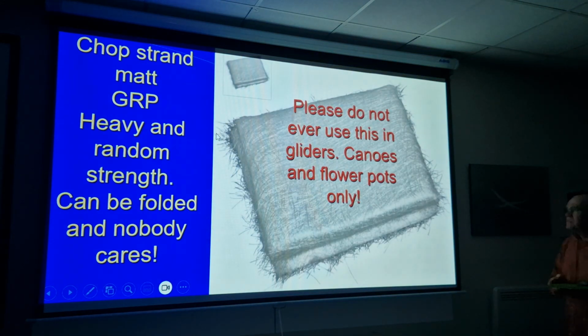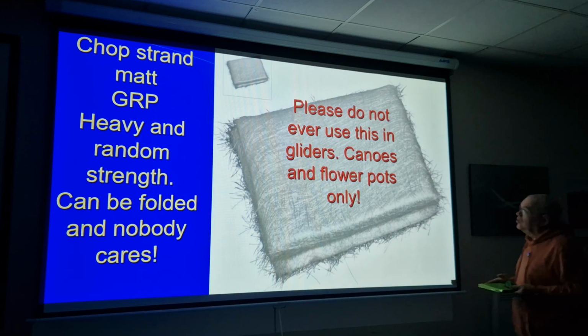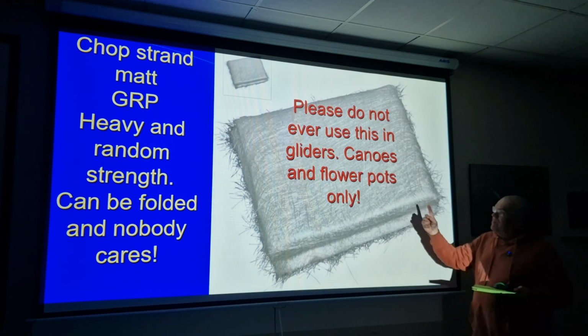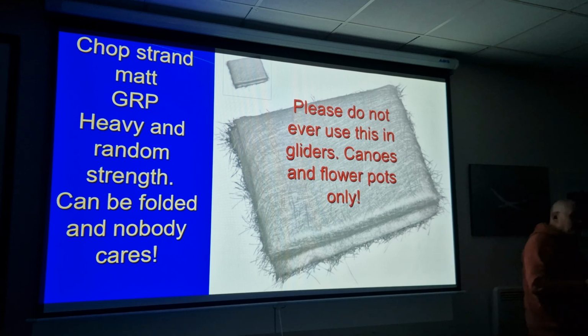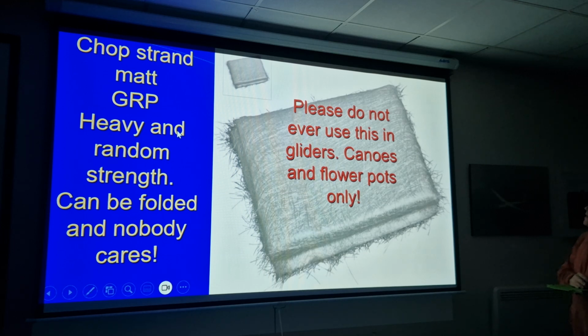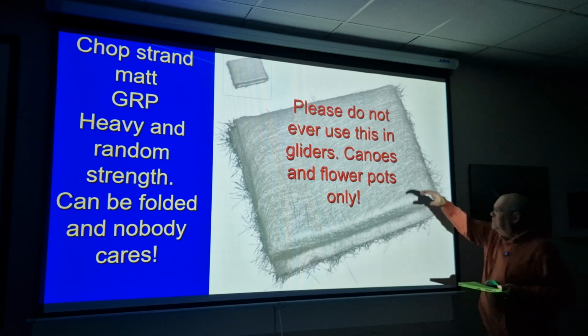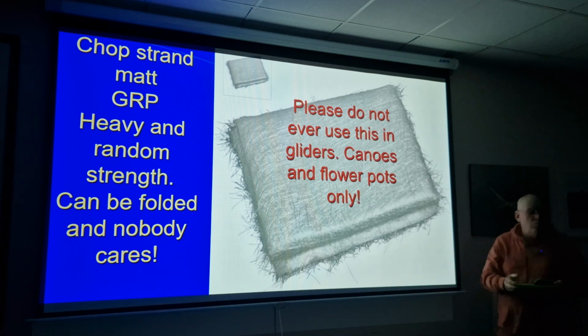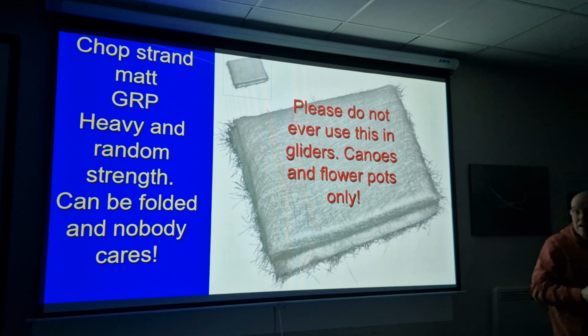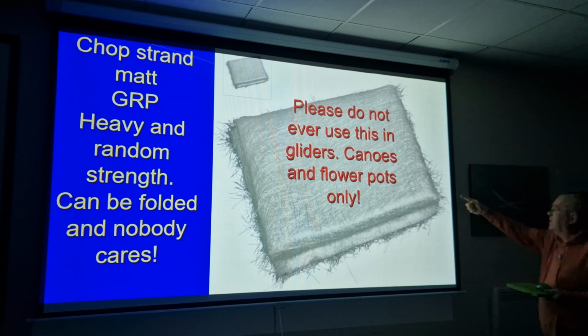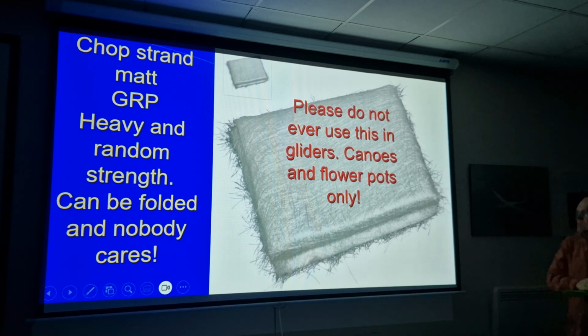This is chopped strand mat. Please don't ever use this in gliders. Canoes, flower pots, that sort of stuff. We do have private owners who genuinely go to Halfords, buy the polyester resins and this stuff, and try and repair gliders with it. So don't. A, it's very heavy. B, it's literally randomised material. It's literally 10 times the weight of a normal glass fibre. And even if you fold this, it also breaks, for all the same reasons the other ones do.